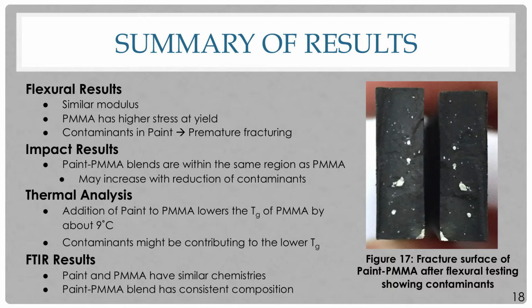Also pictured here are the fracture surfaces from the specimens that broke, and as you can see there are some white specks. These are contaminants that are basically unwanted material that was recycled along with the latex paint that we can't really control. And these were the most likely cause for the fracture that occurred. For impact testing, we found that the impact resistance of the paint PMMA blend was within the same region of the PMMA. And this may even increase if we can somehow find a way to filter out the contaminants prior